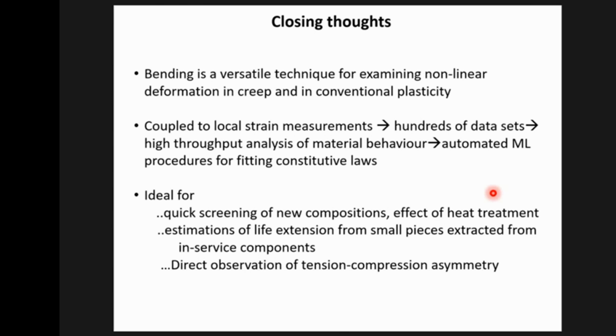So in principle, you could do this in 3 or 4 point bending as well, except the sample volumes will be larger. And in 3-point bending, you're measuring strains directly below the loading point. Whereas here in a cantilever, the advantage is the loading is here and the deformation is happening there. And very rapid analysis of graded systems like you have in welds and so forth.